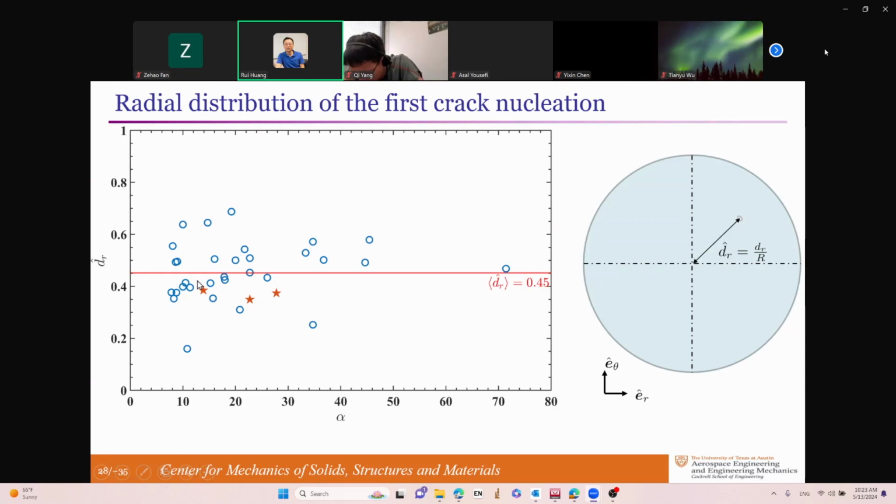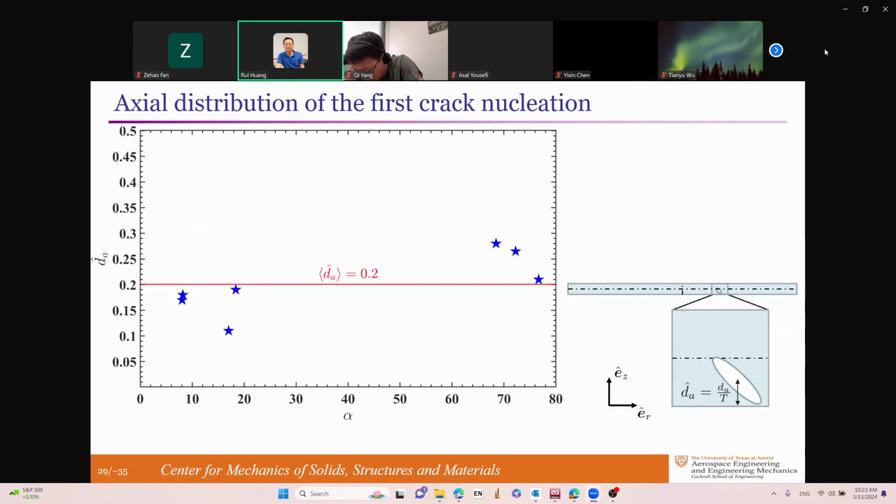There was some speculation that this might have been due to bending asymmetries introduced by the loading device. So we decided to put a cylindrical sleeve around the specimen, a sliding fit, so that it would allow uniaxial motion, but not allow bending. And those specimens also exhibited nucleation at points indicated by the asterisk, so away from the center. We'll file that away.